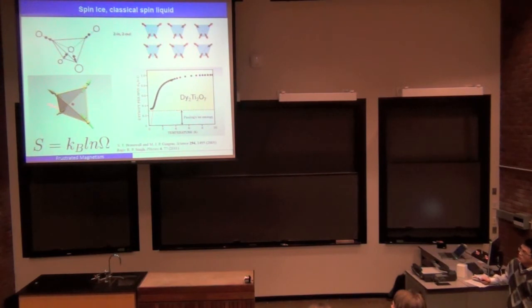If we look at a single spin, then because it can point into or out of the tetrahedra, there are two possibilities at high temperature. So you would expect the entropy to be proportional to the logarithm of 2 times the number of spins in this system. And then when we go down in temperature and integrate the heat capacity peak, you would be able to measure how much entropy is released as you go down in temperature. And it turns out there's a huge amount of entropy not released, even if you cool down to very low temperature. And this is a classical sign of the existence of this huge degenerate ground state.